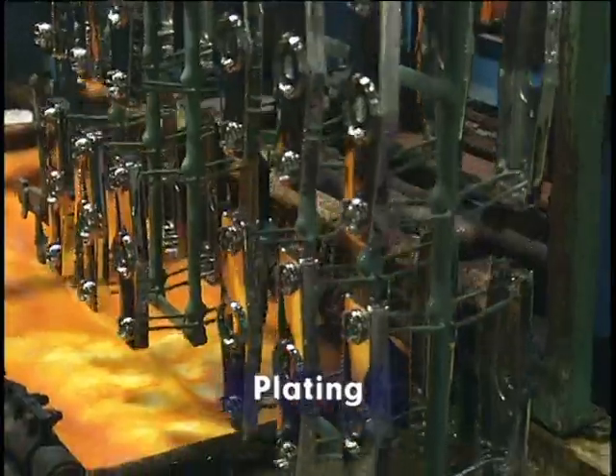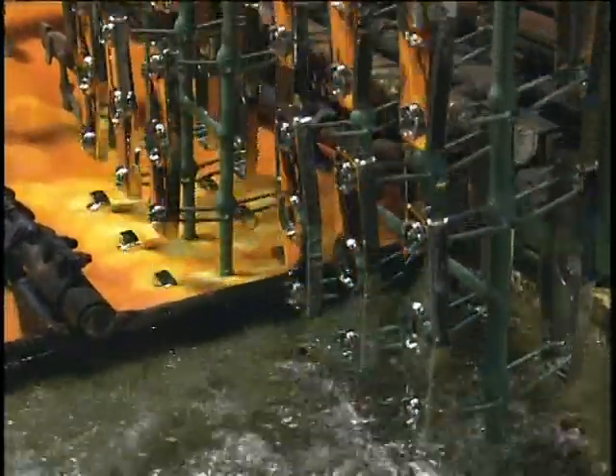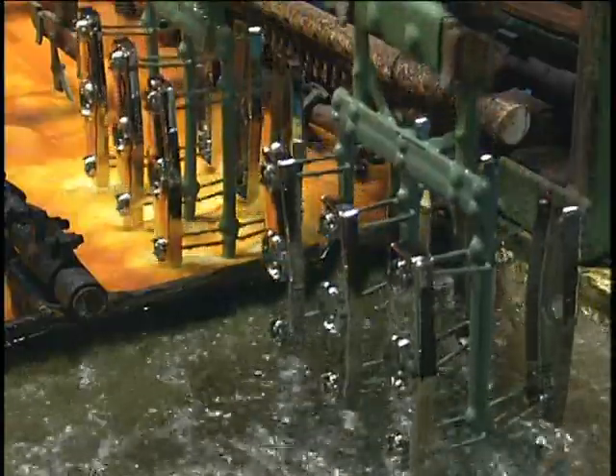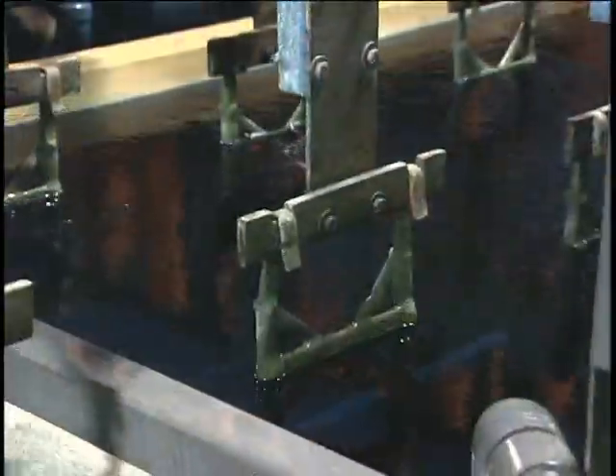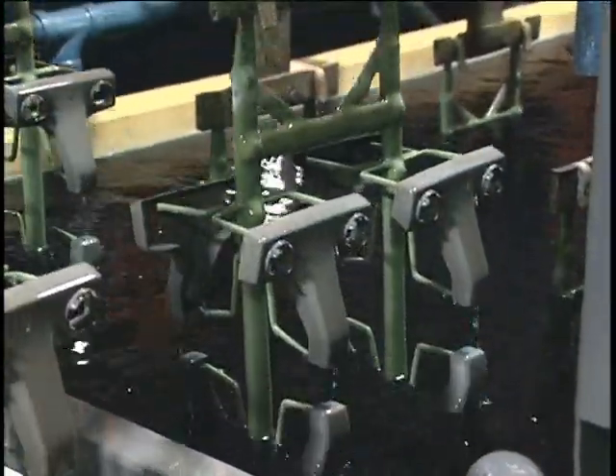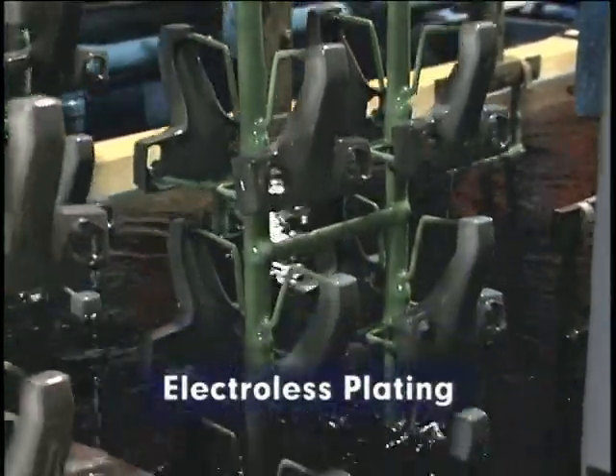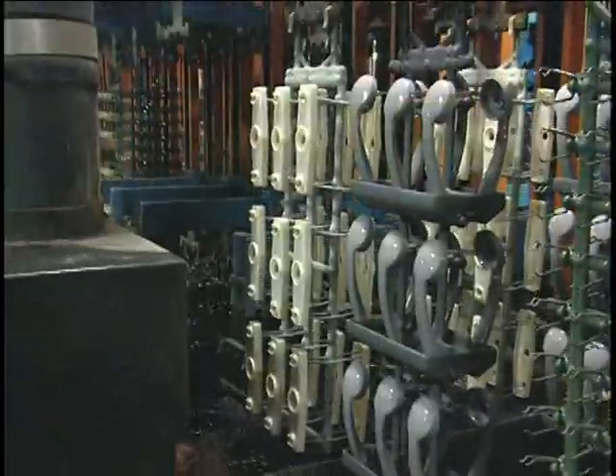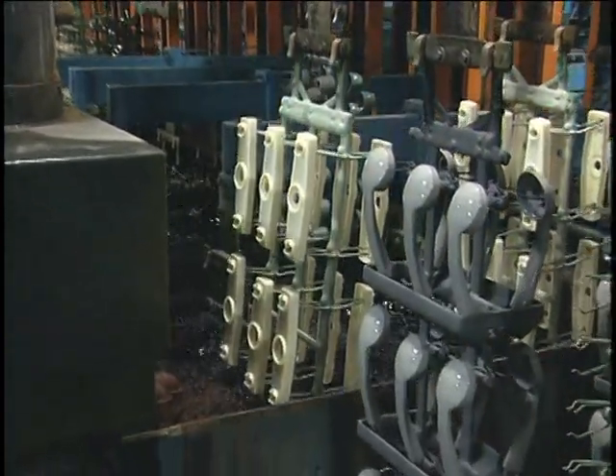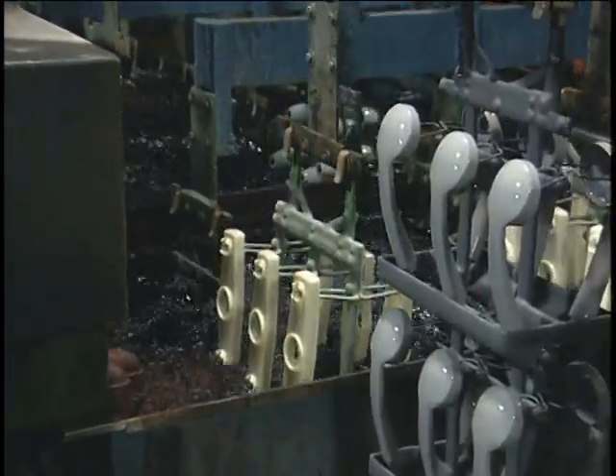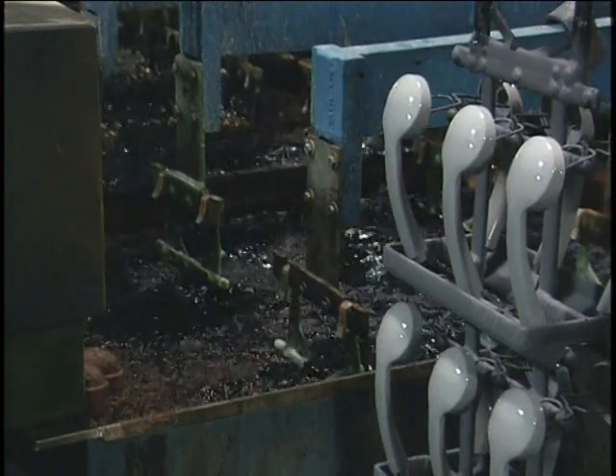Plating is the chemical or electrochemical deposit of a thin metal layer to the surface or substrate of the plastic part. Plating requires the plastic parts to be electrically conductive. To achieve this conductivity, the plastic parts are first subjected to an electroless plating operation. Plastic parts are prepared for electroless plating by submersion in a sulfuric chromic acid bath. This acid slightly etches the plastic substrate surface, creating microscopic pockets or pockmarks.